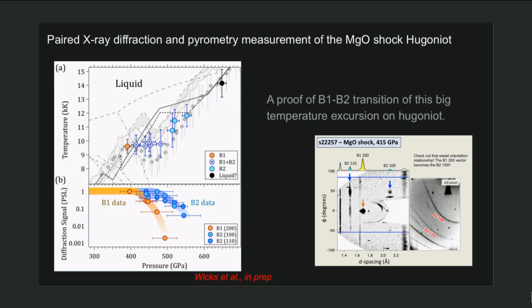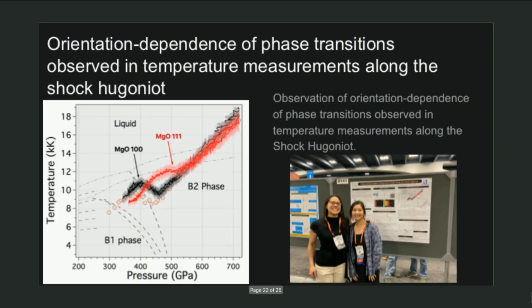One example of a study that we're going to submit very, very soon is how we were able to use in situ X-ray diffraction during shock compression on the MgO Hugoniot, to show that these large excursions in the pressure-temperature Hugoniot that have been measured are correlated with solid-solid transitions, the B1-B2 structural transition. And so having both the in situ X-rays and in situ temperature measurement allows us to correlate these different changes to each other.